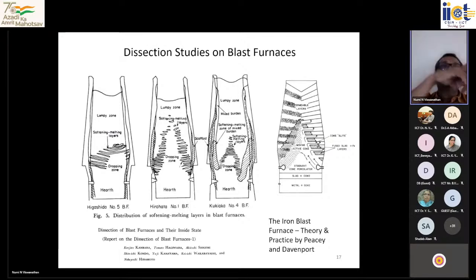And then, like an archaeological excavation, they went into the furnace to see what is inside. And one of the most revealing things was what is known as a cohesive zone, fusion zone, where above this it's all solids, and below it, it becomes liquid. So there is a zone where some solids start to become liquid. So it forms layers. In blast furnace, we charge things in layers, and that is going to control the whole furnace operation, all those things. This was not known at all till that time.